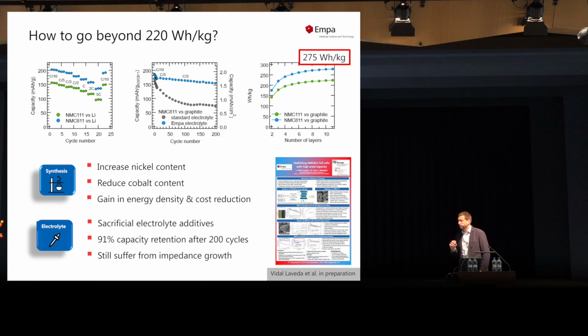So we have been looking into sacrificial electrolyte additives, which we can decompose during the first few cycles, which then form a protective layer, and we were able to stabilize the NMC811 cell here with a capacity retention of 90% after 200 cycles. That's our best result at the moment. We're still suffering from impedance growth. We're also not yet working at high mass loadings, but we're trying to improve this over the next few months.